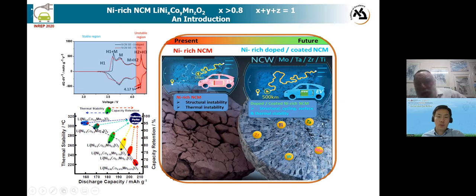But by doping, we can change the picture. If we put dopants like zirconium, titanium, tantalum, molybdenum, tungsten, then we have very compact particles. By having dopants, we change both the surface and the bulk. We have segregation; there is more concentration of dopants on the surface. We will discuss it in a minute. And then we can have more stable materials, which means that we can drive longer with lithium ion batteries based on these cathodes.